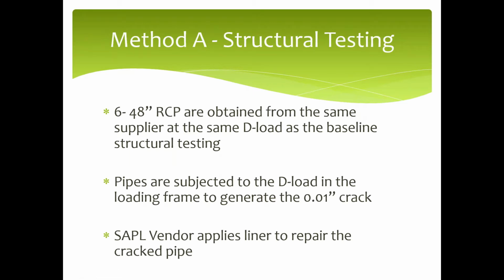So when we get into this for each of our SAPL liner vendors, we'll go out and get 6 of these 48-inch reinforced concrete pipes from the same supplier who gave us the pipe for the baseline test, and we'll get the same deload designation. Then we'll put that in the load frame, load it up, and generate the 0.01 crack. So that's the deload test. Once we get that crack, we'll take it out of the load frame, and then the SAPL vendor will come in and apply his repair to the cracked pipe.